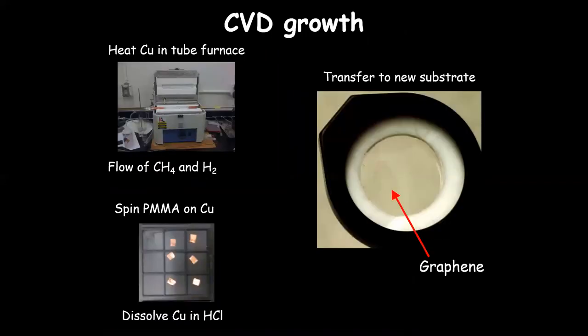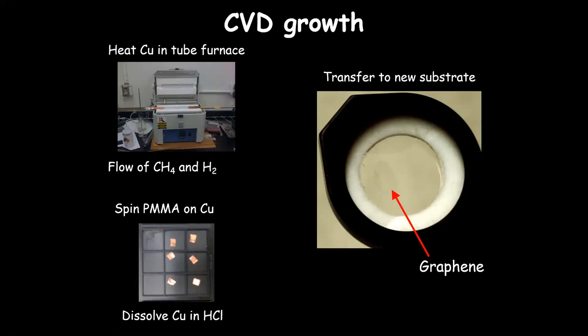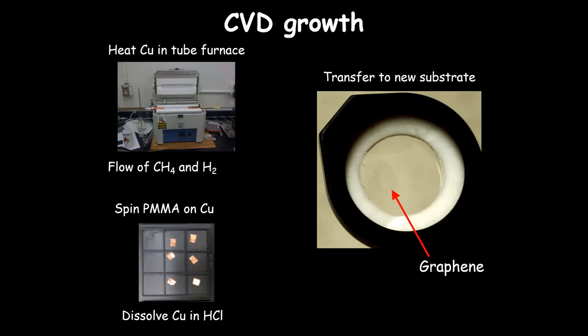You can also make it with other methods like CVD growth. For graphene, we occasionally use CVD to grow these materials. We have a tube furnace, put little pieces of copper inside, flow methane gas and hydrogen through, heat it up to 900°C or so, and a monolayer of graphene grows on the copper. We then dissolve the copper away in acid and transfer the graphene to another substrate — something like a quarter-inch piece of graphene on a one-inch optical window. With exfoliation we're limited to tens or maybe 100 microns; CVD lets us grow millimeter or inch-scale graphene.